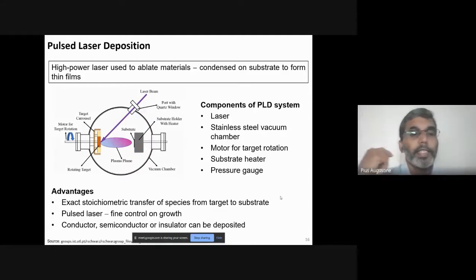When it hits this target, extremely high temperature will be produced there, and a plasma plume will be produced. That material will be suddenly evaporated, and a plasma plume of ions of this material will be released. And that is what is shown in that color. That will be directed towards a substrate, which is placed on the substrate holder just perpendicular to that. When this plasma plume reaches the substrate, exactly the stoichiometry of the material will be maintained, and the same material will be deposited. But in many systems, sometimes the stoichiometric transfer may not be possible. Originally, this pulse laser deposition was very popular, particularly in superconducting systems like yttrium barium copper oxide, YBCO.